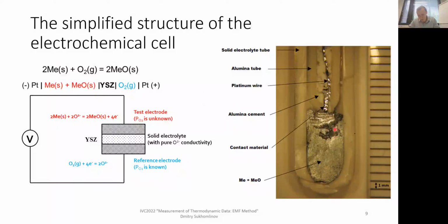Rather small flow that it doesn't disturb equilibrium. And then we have platinum lead wire connected. Often we need to find suitable contact material because platinum might be reactive with your sample, with your test electrode. So we need to find some noble metal or graphite or perhaps some oxide, chromium oxide. Researchers have been creative with contact material because that's one of the possible limitations of this method.